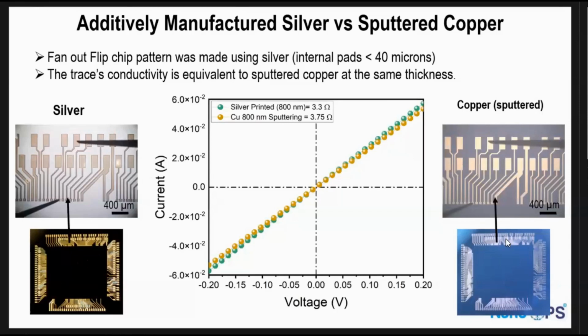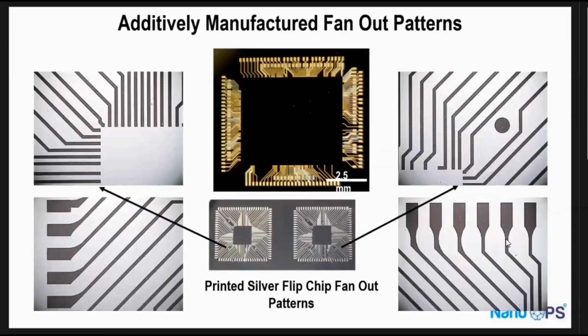So we printed it, and then they wanted to compare that. We printed silver. I'll talk more about the traditional printing ink that's available later on. But this is silver printing. And then they wanted to compare that to copper. So we compared the same exact pattern using sputtered copper. And you can see the performance is pretty close. These are the same thickness and the same pattern. So that gave them confidence to move forward with the printed pattern, for example.